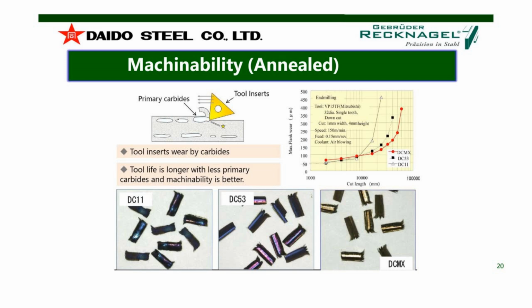The machinability, as I mentioned in the beginning, is really outstanding with DCMX. The pictures below show us the chips during the milling process. It's in annealed condition, that means rough machining. And you can see for the D2 grade, we have dark blue colored chips. That means we had a very high temperature in the milling process.